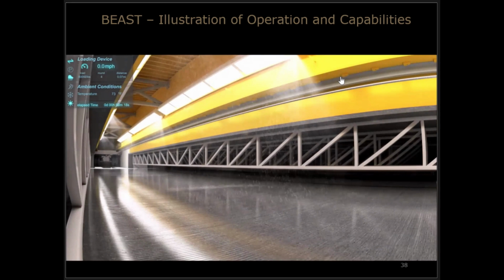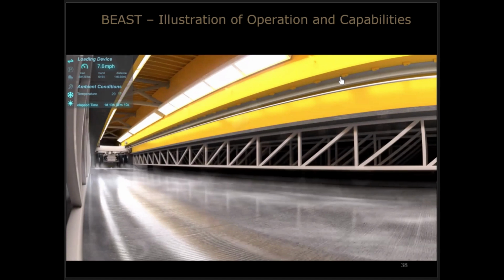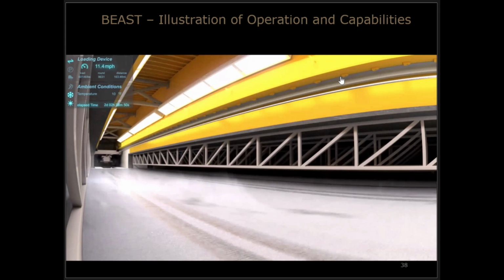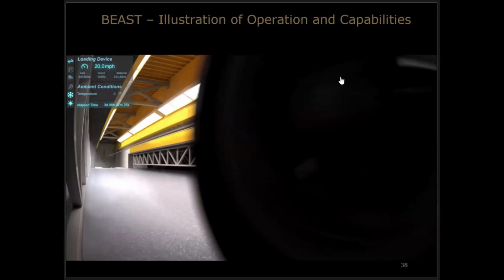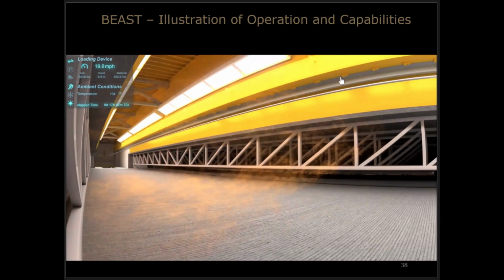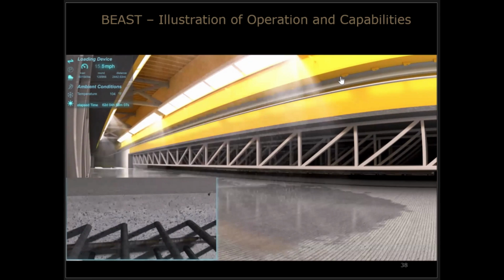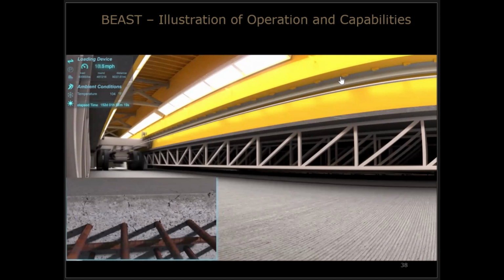So you can control environmental conditions. So we have spraying, but not from the ceiling. It's done from the side. You can control temperature. If you look very closely at the upper left corner, you will see the temperature is going to freezing right now. And now it is heating up, going to a much higher temperature. So the objective is really to drive temperature sufficiently low and sufficiently high to have freezing and thawing. And so this was the idea. Yes, we will have a number of cycles.